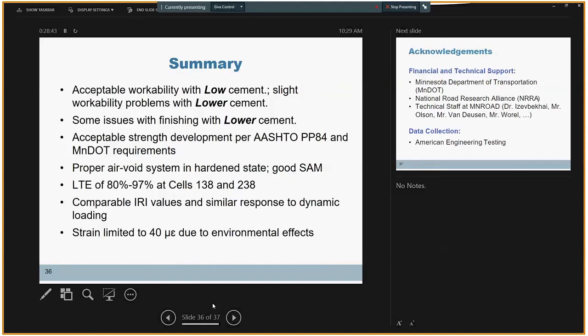So in summary, based on the first year data we have gathered up to date, for the concrete mixture prepared with lower cementitious material as low as 470 pounds, there were no issues with mechanical properties or durability of the concrete itself. A bit concerned about workability of such a concrete, but overall the in situ measurement suggests that we have comparable performance with low cement with 500 pounds per cubic yard, and we will keep monitoring the data and update you with further data we get. But overall, so far, both pavement sections are performing well and as expected.